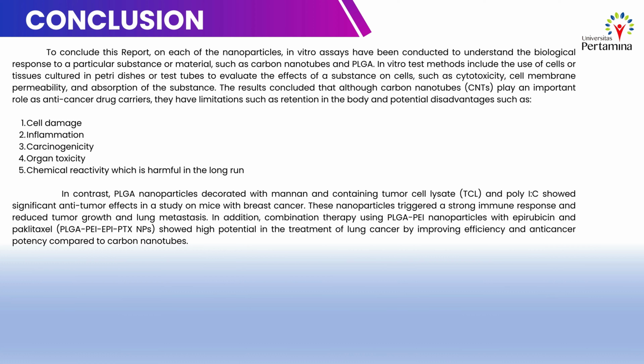In contrast, PLGA nanoparticles decorated with mannan and containing tumor cell lysate (TCL) and poly I:C showed significant anti-tumor effect. In a study on mice with breast cancer, this nanoparticle triggered a strong immune response and reduced tumor growth and lung metastasis. In addition, combination therapy using PLGA-PEI nanoparticles with epirubicin and paclitaxel, PLGA-PEI-EPI-PTX NPs, saw high potential in the treatment of lung cancer by improving efficiency and anti-cancer potency compared to carbon nanotube.